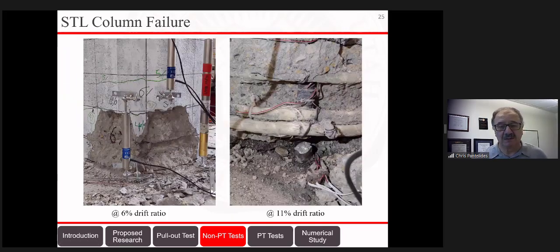The failure of the STL column at 6% drift ratio, we saw spalling. This spalling was about a foot, 300 millimeters high at the base. And the cracks progressed until 11% drift when the outer steel bar and 2 turns of the spiral fractured, as you can see here. And this happened at 11%. 11% is an unbelievably large drift ratio. It will never happen during an earthquake, unless the earthquake is really, really very strong.